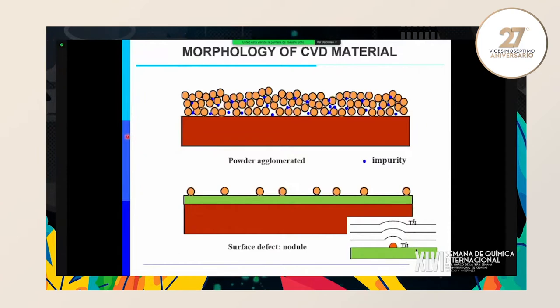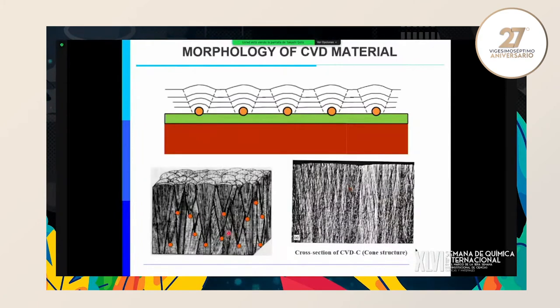A part of these nanoparticles may deposit on the substrate, then the film becomes a porous agglomerated powder. This microstructure is likely to contain impurities, and it is not a good microstructure of CVD materials. Even if nanoparticle formation is not so significant, some particles still deposit on the surface. And these nanoparticles become the nucleation sites of film formation. This is a very common microstructure of CVD.